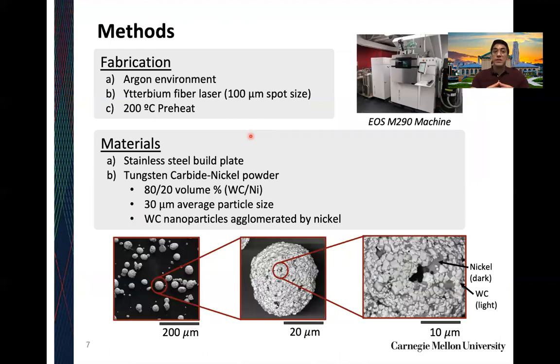So in our 3 experiments, we had very similar experimental setups. We used an EOS M290 machine, which is an industrial metal 3D printer for the selective laser melting process. Within the chamber itself, it was an argon environment, but that doesn't mean that there weren't minor traces of oxygen in there. The machine uses an ytterbium fiber laser, which is near infrared, around 1 micron in wavelength, and it had about a 100 micron diameter spot size. And we just used a very standard 200 degrees Celsius preheat on the substrate.